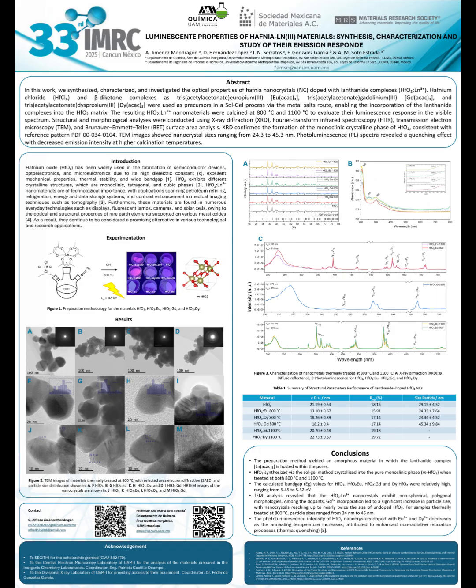material. Experimental procedure. The synthesis was carried out via a sol-gel method, following the metal salts route. Hafnium chloride, HfCl4, was used as the hafnium source, and lanthanide dopants were introduced as beta-diketonate complexes. Specifically, tris acetylacetonate europium III, tris acetylacetonate gadolinium III, and tris acetylacetonate dysprosium.